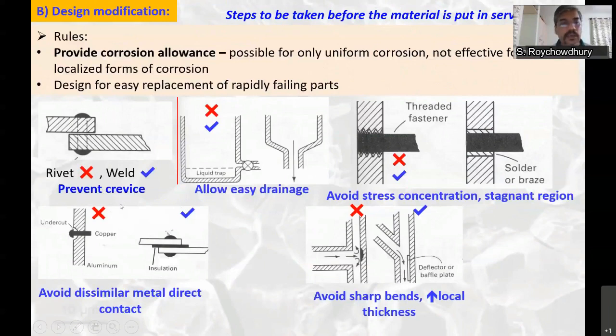Crevices should be avoided at all costs. Like two metals in physical contact, you can have a crevice here. There is a tight gap in between. So they should be avoided, because that leads to crevice corrosion. So instead of riveting, you do welding. One should do welding because rivets form these crevices very easily.